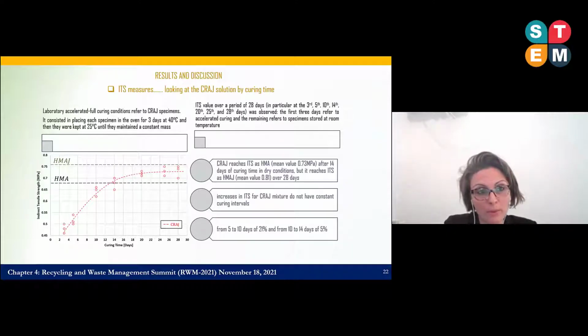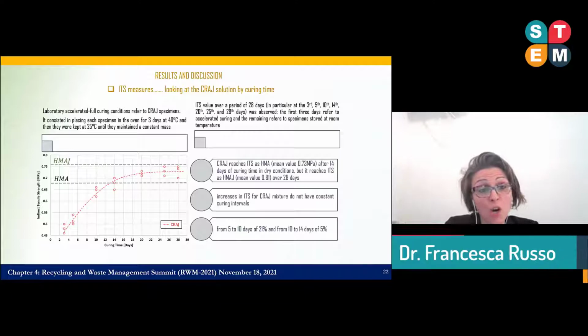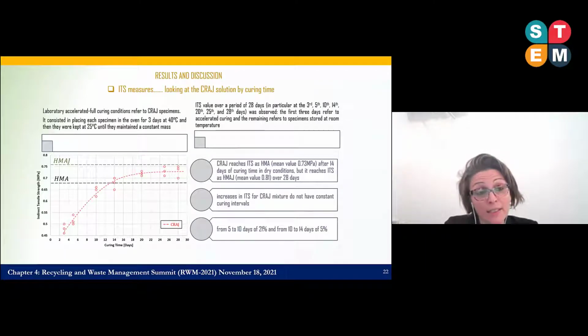A few conclusions about that. Looking at the cold recycling of old asphalt mixtures in terms of indirect tensile stress, it can be observed in the graph that the cold recycling asphalt mixtures reach the ITS value of the traditional hot mix asphalt after 14 days of curing time in dry conditions, but they reached the ITS of innovative hot mix asphalt that contains jet grouting waste in dry conditions only after 28 days. It should be noted that increases in ITS for the cold recycling mixture don't have constant curing intervals. In fact, from 5 to 10 days and from 10 to 14 days, the ITS increases a lot, almost around 20%, and around 5% in the last steps.